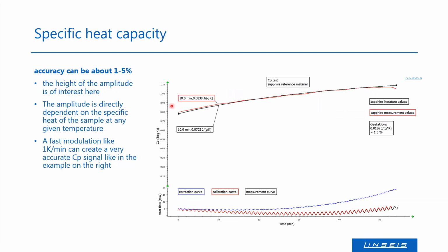And to prove this, here you can see the black curve is the literature value of sapphire, and the red one is our sample measurement with sapphire. The biggest deviation here is at this point, and it's about 1.5%. So I think it's pretty good. What's important is that at the very beginning of the measurement and at the end, the values could differ from the literature